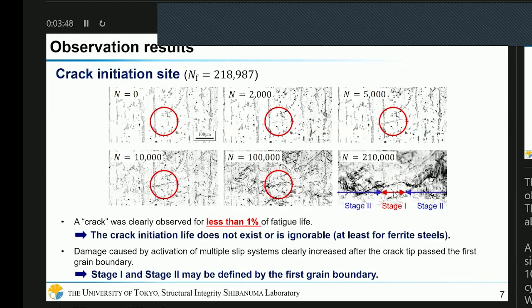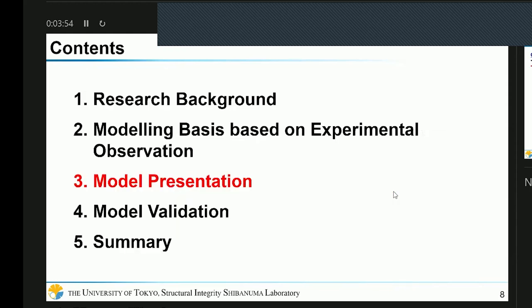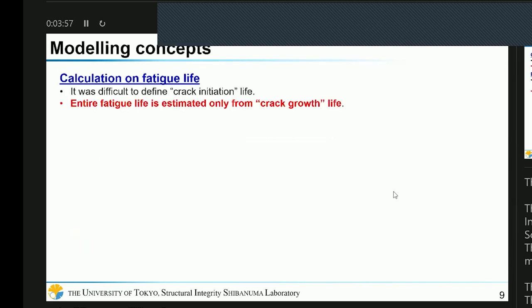So we developed a model based on these experimental facts. I will show you the outline of the model presentation. This slide shows the modeling concept. And the first one is the calculation of fatigue life. Based on the experimental observation, it was difficult to define crack initiation life, though it is a very common approach for predicting fatigue life. But we ignore it. The entire fatigue life is estimated only from crack growth life. This is the most important concept of our model.